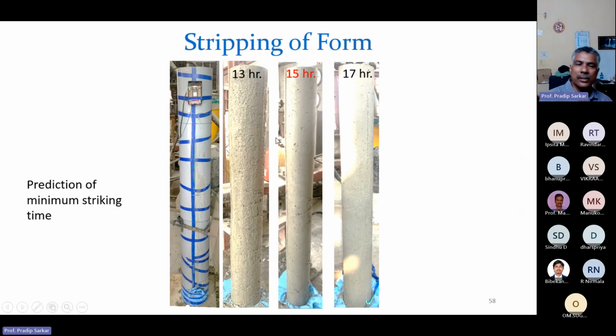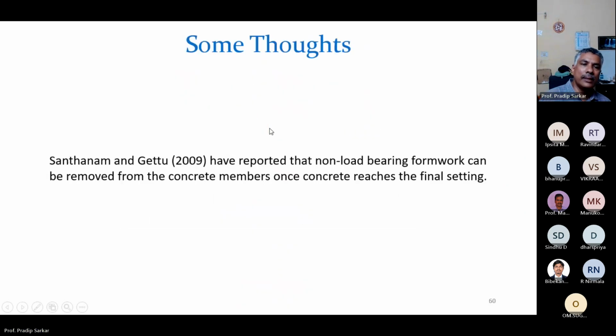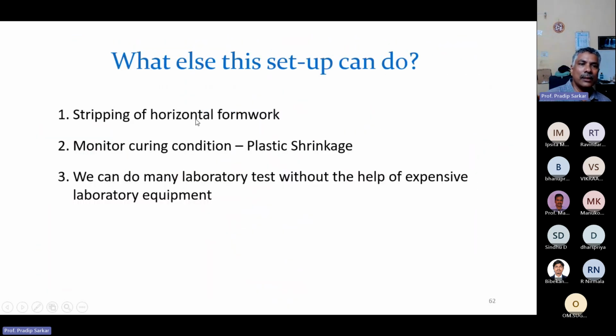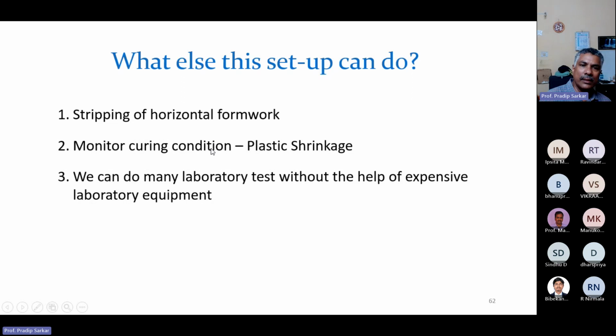So apart from stripping of vertical formwork, this method can be used in other ways, like stripping of horizontal formwork, load bearing formwork, and monitoring curing condition for plastic shrinkage. You know, many times at site curing is not done by the contractor, but that information does not reach the construction manager. But if we can use this system at site, we can see an alert on our mobile phone when it requires curing, when plastic shrinkage cracks are impending, right? So that information we can get.